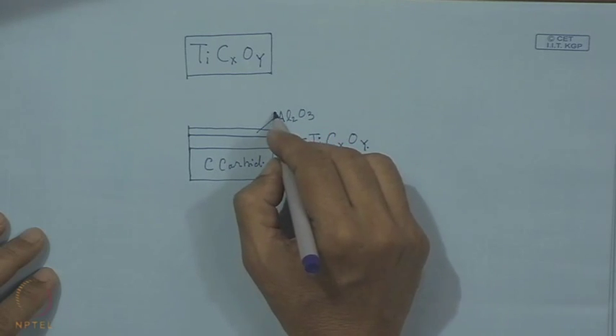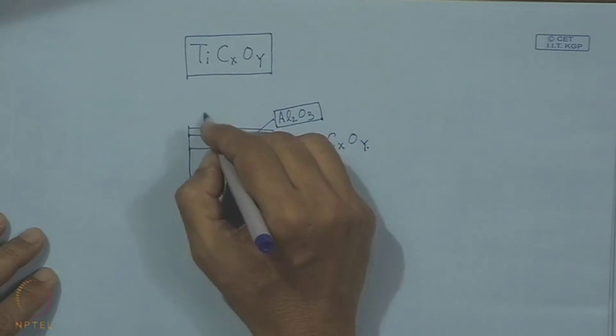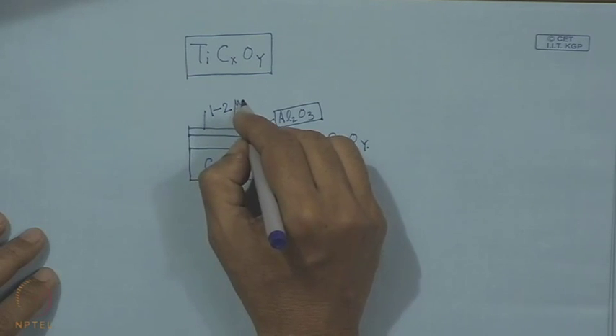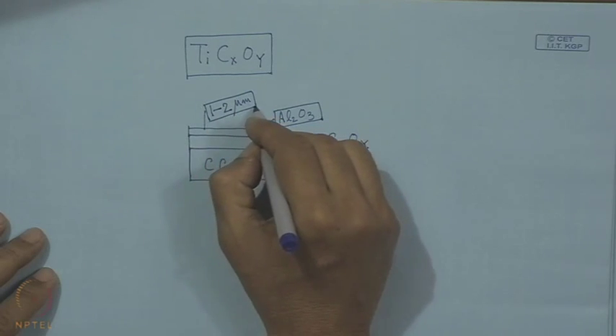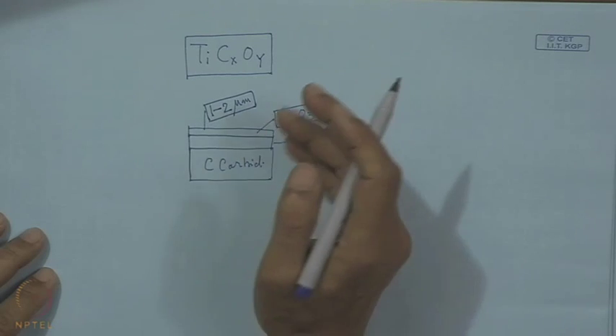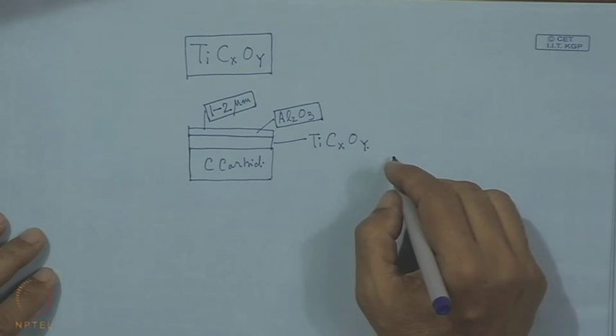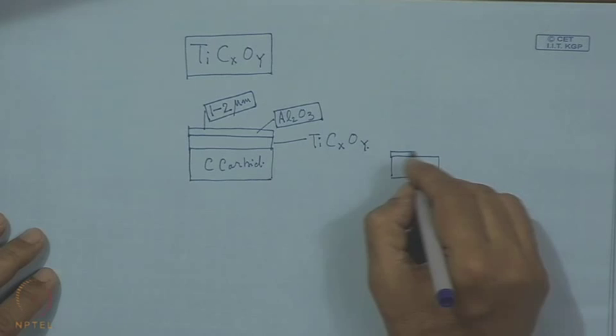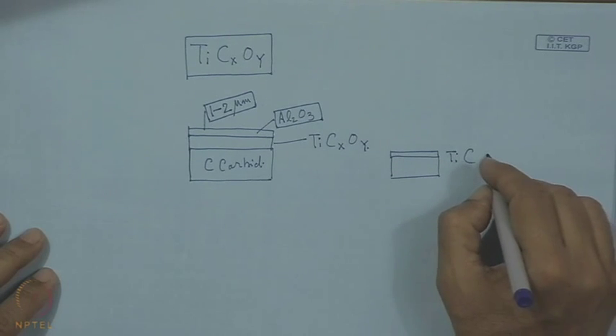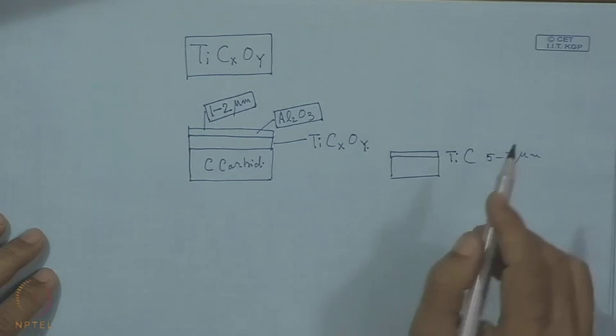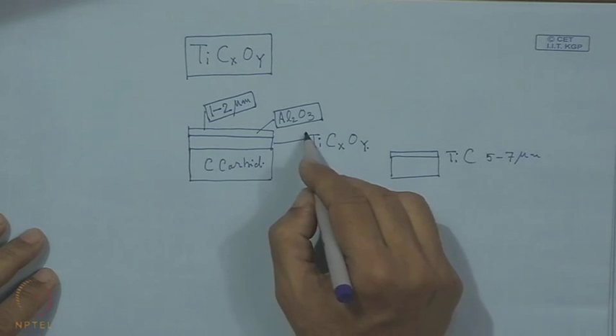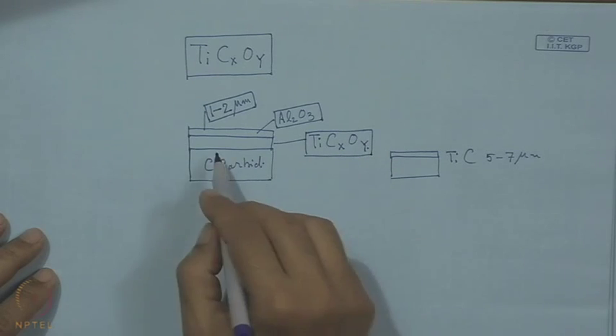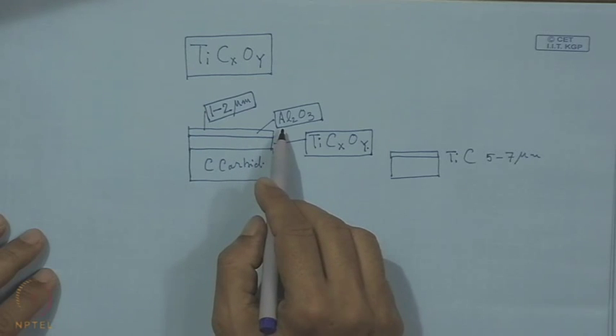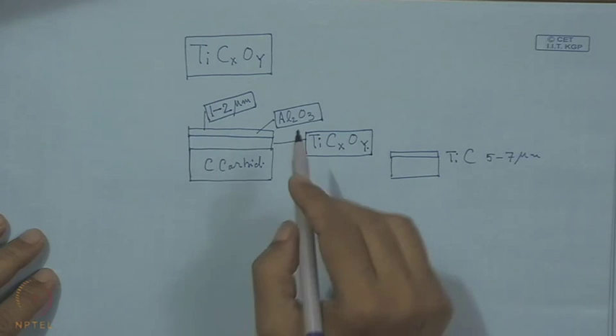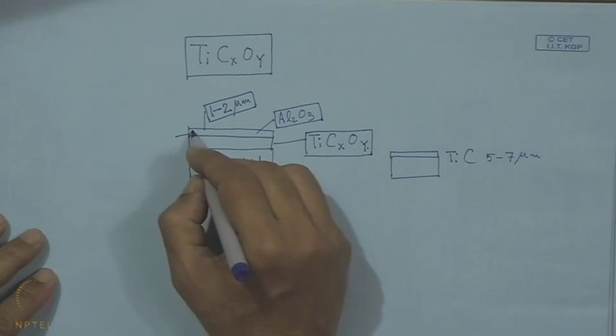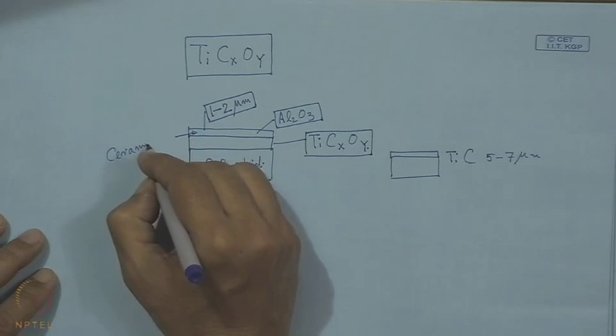And it must be mentioned that this aluminium oxide is just in the order of 1 to 2 micron, and with this 1 to 2 micron, the performance of the tool can be remarkably increased in comparison to a monolayer coating of TiC. So, if we have here TiC, which is say 5 to 7 micron thick, but over that, instead, if one puts this titanium oxycarbide as the intermediate layer, and over that we have a 1 to 2 micron thick aluminium oxide coating, then this coating material is now behaving like one ceramic tool.